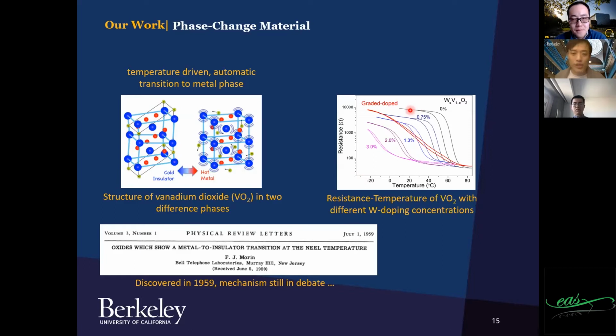So upon phase change, it will change from a dielectric insulator to a metal. And our group also used a tungsten material to dope the VO2. With a higher tungsten concentration in VO2, the phase change temperature of this material will be decreased. So in this approach, we can simply and accurately control its tungsten concentration to tune its phase change temperature to room temperature.